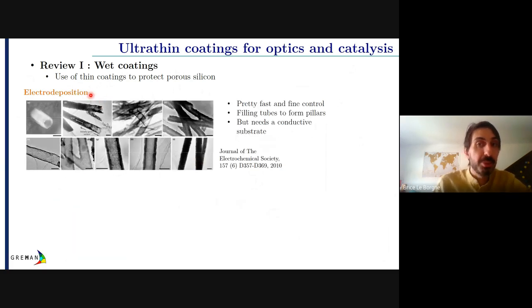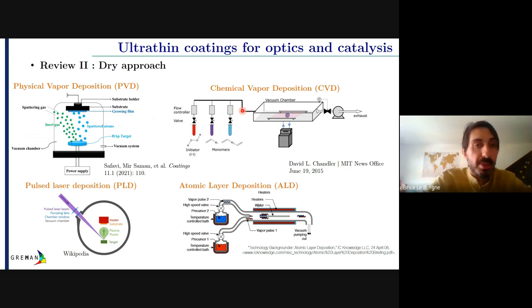You of course have electrodeposition, which is very famous and a technique that has been used for many years. So it's pretty fast. You have fine control. It's possible to fill tubes to form nanopillars, for instance. We often have this kind of application or presentation in either Netpore or PSST seminars. So it's great. But you need a conductive substrate, so that can be an issue. So those are the three techniques I'm presenting for the wet coatings. You of course have a lot of different ones or variations.